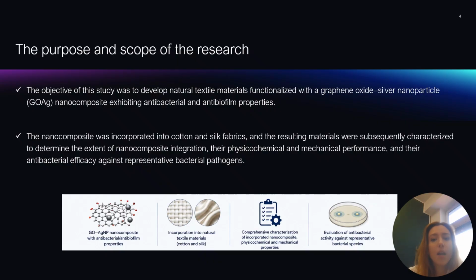Considering the growing threat of antimicrobial resistance and the critical role of biofilm in persistent bacterial infection, the aim of this study was to develop natural textile materials functionalized with the graphene oxide and silver nanoparticles nanocomposite, exhibiting antibacterial and antibiofilm properties. The nanocomposite was incorporated into both cotton and silk fabrics, and the resulting materials were evaluated in terms of nanocomposite integration, physicochemical and mechanical performance, and antibacterial efficiency against representative bacterial pathogens.